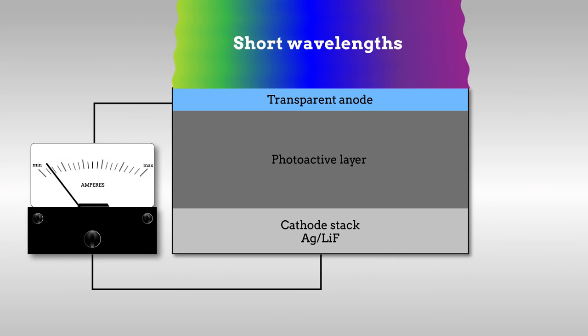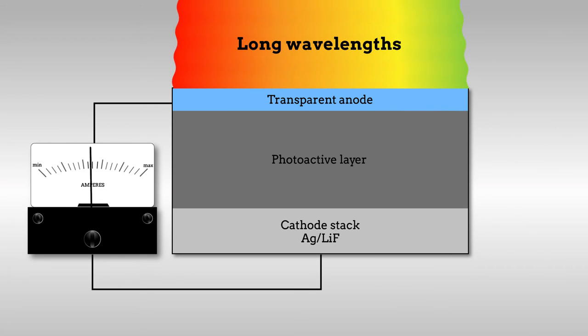Short wavelengths of light generated charge carriers mainly near the surface of the active film, preventing efficient charge collection. Longer wavelengths, however, generated charge carriers deeper in the active material, making their contribution to the collected current signal much greater than the contribution from shorter wavelengths.